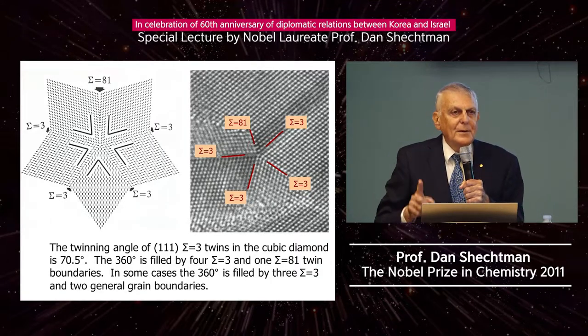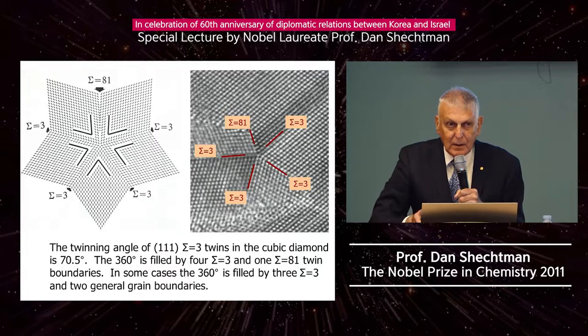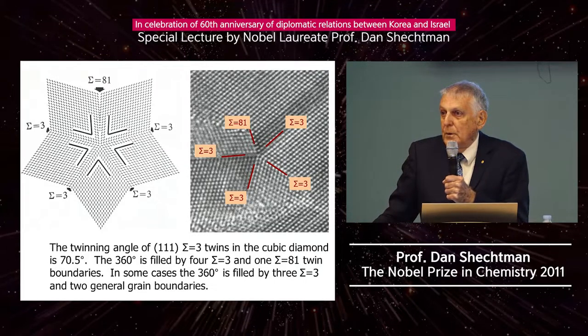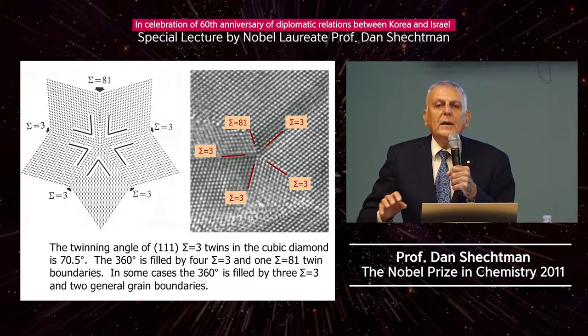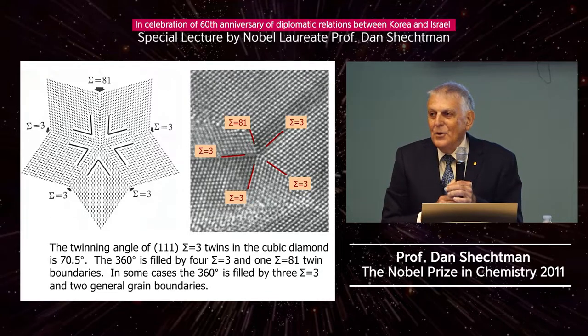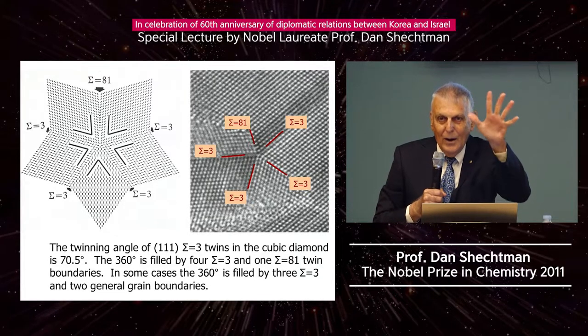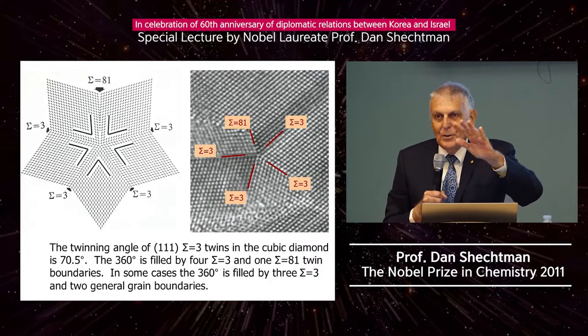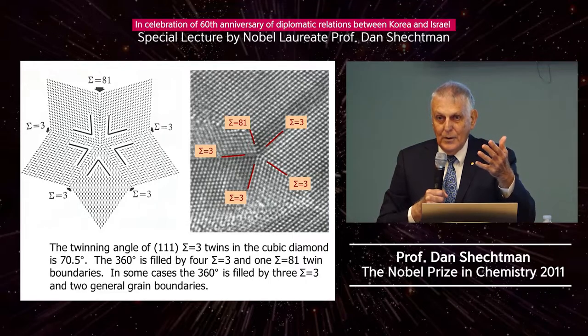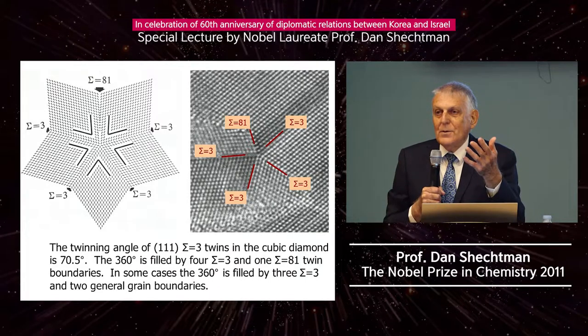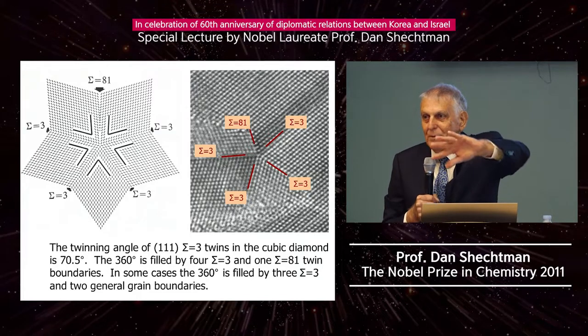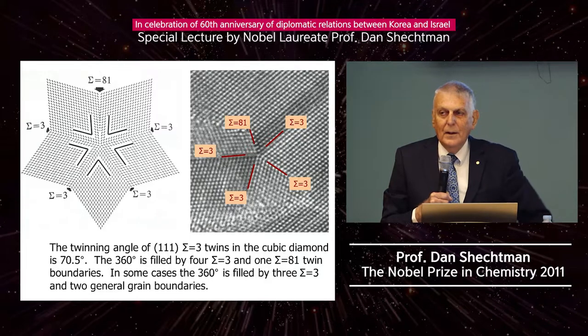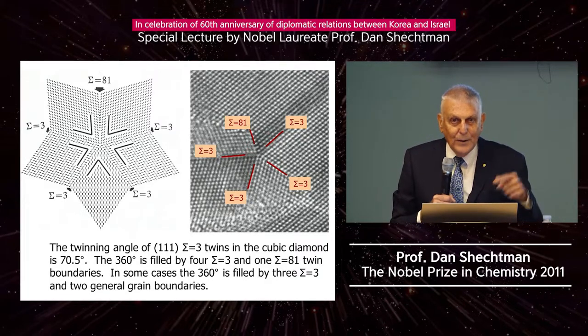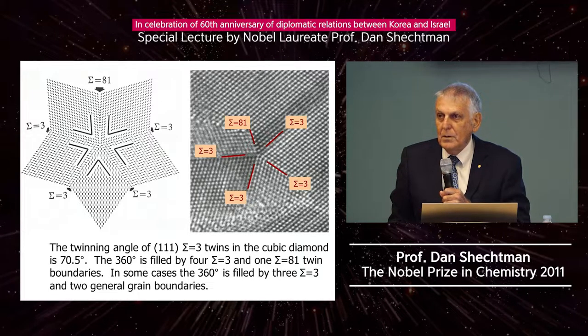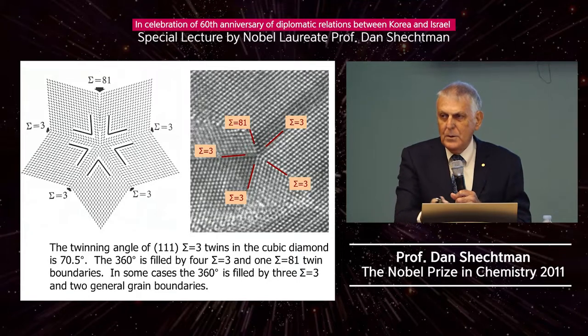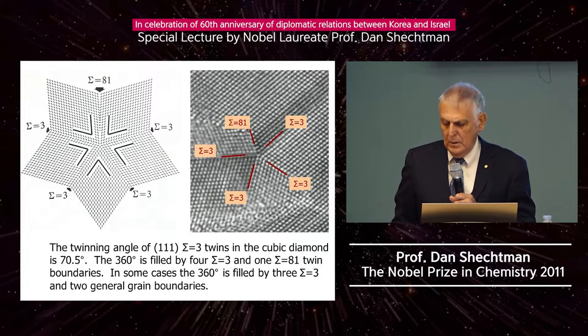Now, if you take a diffraction pattern from just one of these crystals, you'll have a periodic diffraction pattern because it's a periodic structure, diamond. But if you take a diffraction from all five of them together, then you have five superimposed diffraction patterns. One, two, three, four, five, 72 degrees to each other, and the diffraction pattern will have five-fold rotation symmetry because it's a combination of five diffraction patterns. Of course, it will have five-fold rotation symmetry, but it doesn't come from one crystal. It comes from five crystals. This is exactly what I thought when I saw the picture. I said, these are twins, because I had taken such pictures years before. I knew about five-fold rotational twins.